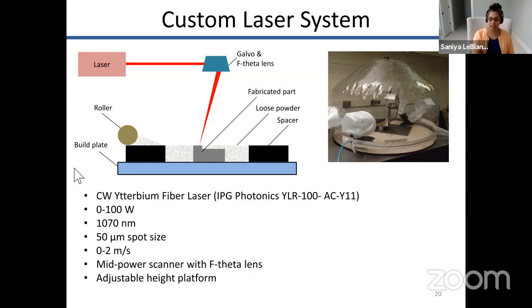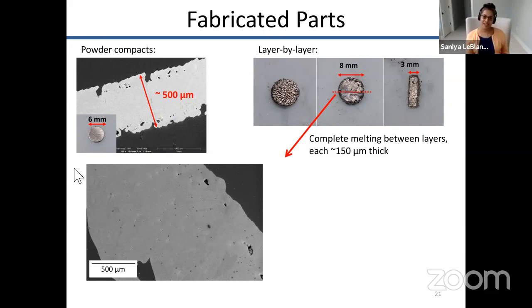And so I'm going to jump right to the chase. After a lot of research work to figure out how to make this happen, we have been able to build up parts out of thermoelectric material. So you see here a part that is 8 millimeters wide for the disc and 3 millimeters wide for this bar structure. And we've gotten parts that are about 85% relative density, so somewhat porous, but a decent density for some initial parts.